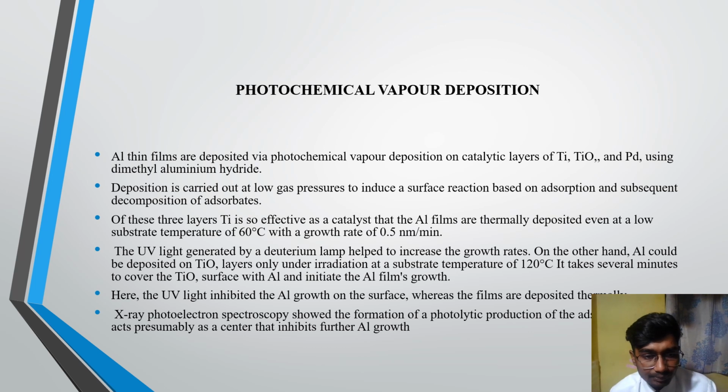The X-ray photoelectron spectroscopy shows the formation of photolytic products of the adsorbates, acting as a center that presumably inhibits further aluminum growth.